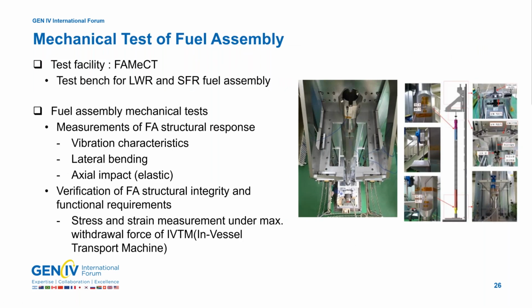And this is for the mechanical test of fuel assembly. We used the existing facility, which was used for the light water reactor fuel assembly mechanical test. So we made some slight changes to accommodate our SFR fuel assembly here by installing some sensors. We did measure the fuel assembly structural response, like vibration characteristics, lateral bending, and axial impact.